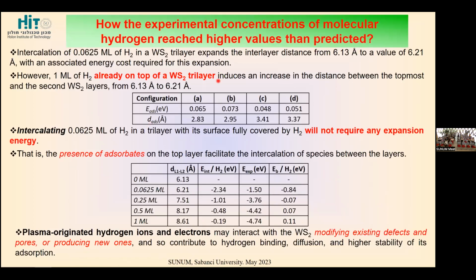So how did the experimental concentration of molecular hydrogen reach higher values than predicted? First, we have more than one monolayer of hydrogen, and then, as I told, though intercalation is not an energetically favored process, because of plasma and because of defects and pores in our materials, there is some penetration of hydrogen. But there is one more property that we discovered for our hydrogenated materials. When we have just one monolayer of hydrogen on the very surface, this monolayer induced the expansion between the layers in the deeper layers, and then we will use it for another part of our research that I will talk about in a few minutes.